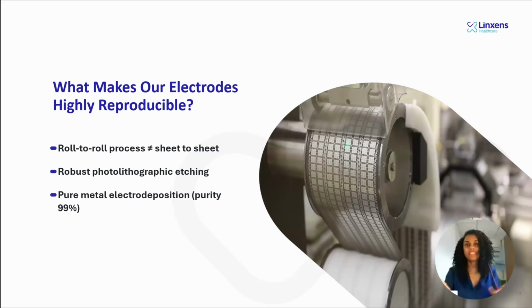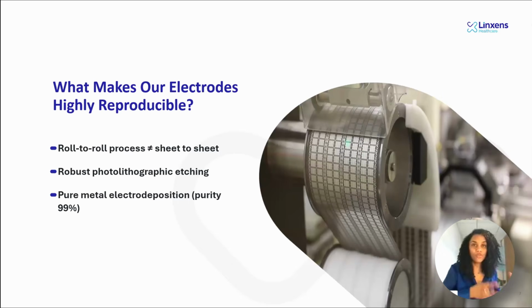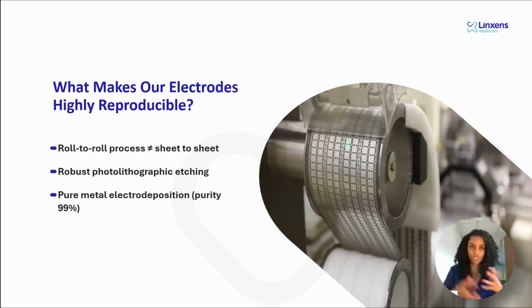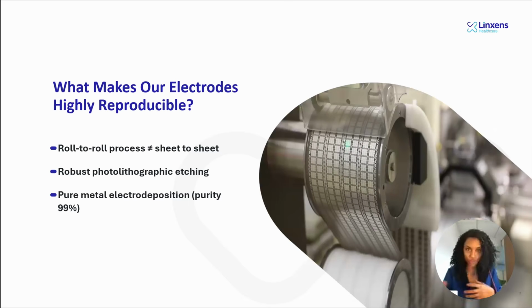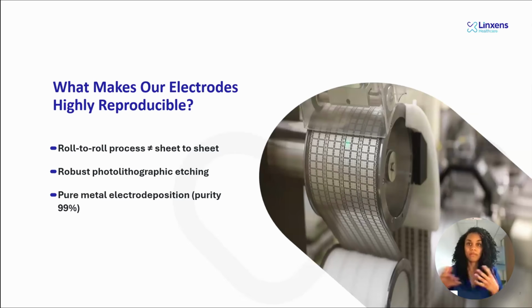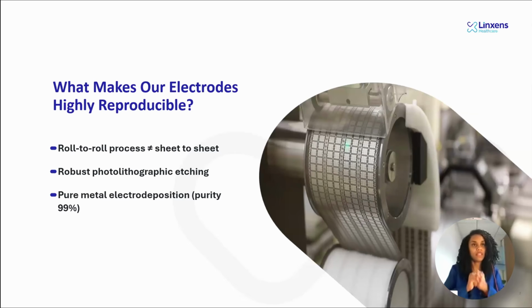So for example, in screen printing, you work on sheets. And sometimes when you start with the first sheet, and then use another sheet, the viscosity and the rheology and the property of the ink change during the time. And this is what we don't have with our roll-to-roll process, because one will see the same process at the same time.